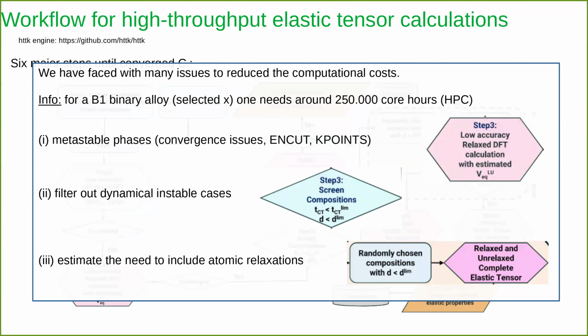So, during the development of this workflow, we have faced many issues on how to reduce the computational cost. Just as an info: if I take a cubic binary alloy at a certain concentration, let's say this 50-50 titanium aluminum nitride already shown, one needs around 250,000 core hours on an HPC computer to get the elastic constants calculated. This is too much.